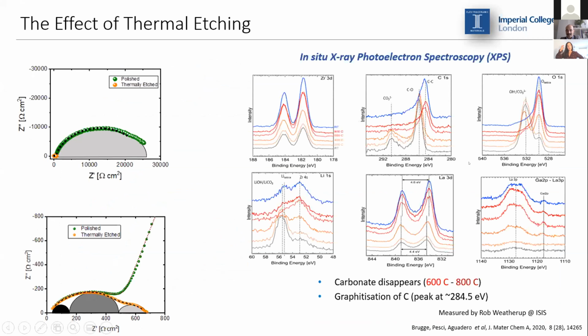Going back to the impedance I showed you earlier and the effect of thermal etching, we decided to carry out XPS in order to understand the role of thermal etching on LLZO. What we can see here is an in situ X-ray photoelectron spectroscopy measurement in which we were following all the garnet components and carbon, at increasing temperature from room temperature up to 800 degrees. Especially from the carbon spectra, we see the disappearance of a peak attributed to carbonates when the temperature reaches 600 degrees.